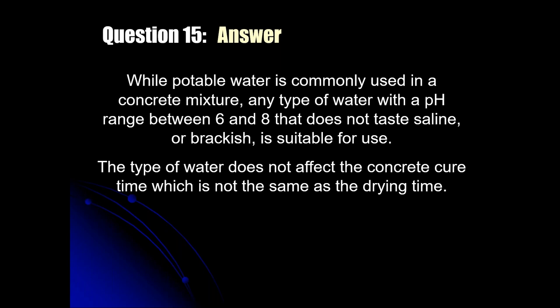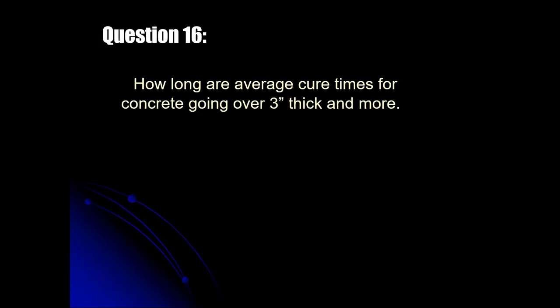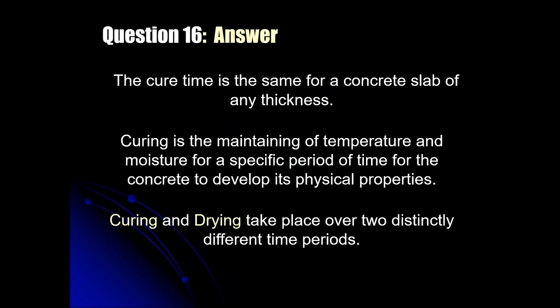By and large, potable water is used in a concrete mixture, but it doesn't necessarily have to be potable as long as the pH of that water is within that 6 to 8 range, and it doesn't taste saline or look brackish, if you will. It's considered acceptable, but the largest percentage is potable water or drinkable water. It doesn't affect the cure time, as I said, which is totally different than the drying time. So here again, how long are the average cure times for concrete going over 3 inches thick and more? Well, the cure time is the same for a concrete slab, regardless of its thickness.